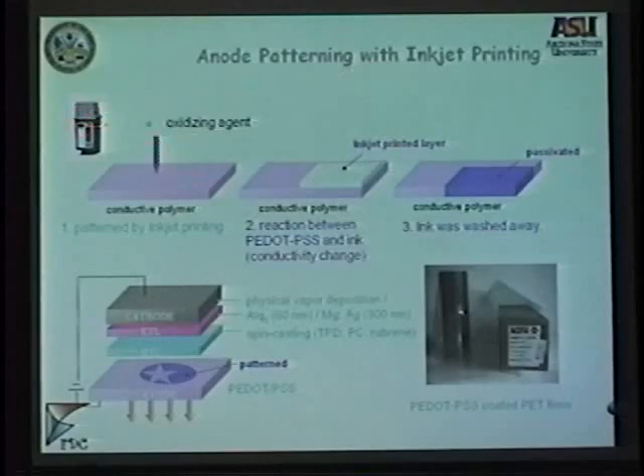And we put an oxidizing agent in here. So in this experiment, we're printing oxidizing agent on top of a plastic that has already been coated with PEDOT. Once you print the oxidizing agent on the PEDOT, you process it just like you process semiconductor wafers. You wash it with DI water and dry. And that's all you have to do. Then later, you can put either a single layer of emitter like a polymer, for example, or multiple layers of small molecules. It depends on your application. There is no further patterning whatsoever after the printing of the oxidizer.